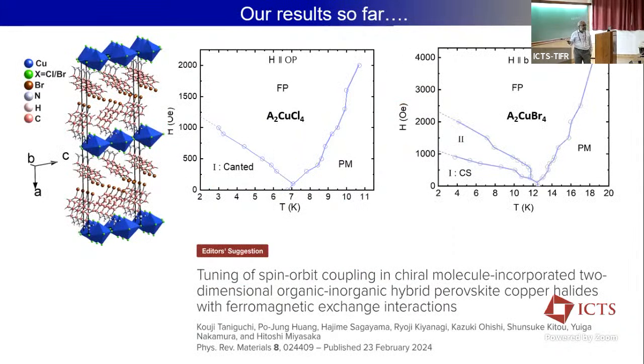So based on the detailed measurements, we proposed this kind of phase diagram, where for the chlorine case we see a canted structure to a fully polarized ferromagnet. For the bromine case, we go from a conical spin spiral with some period, because we see two peaks in the AC susceptibility, to another period, that is your second, and then we get to A2CuBr4.